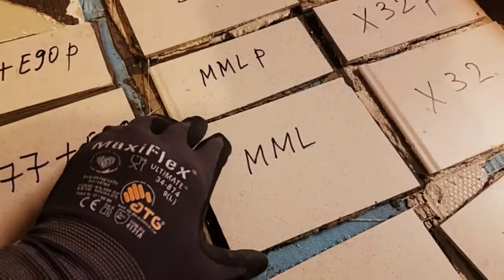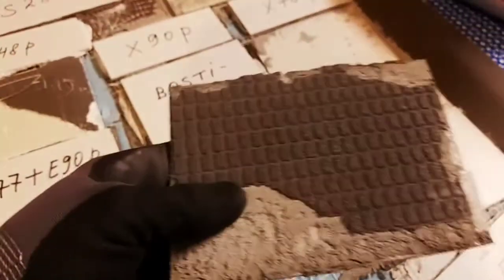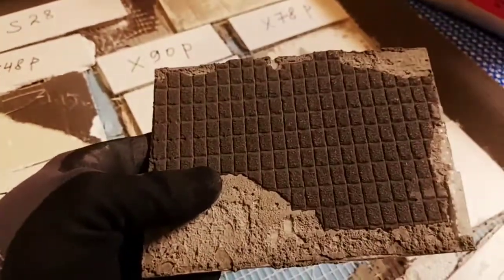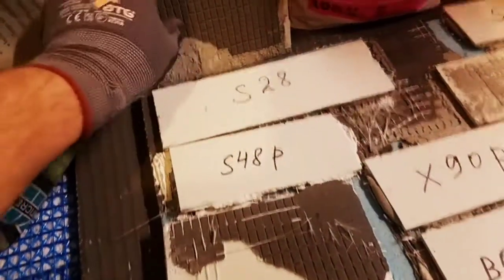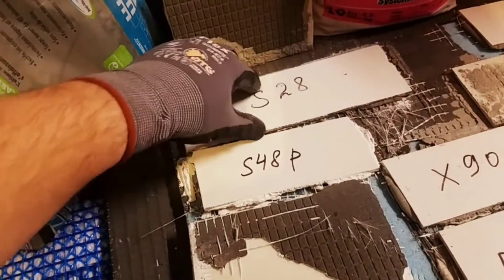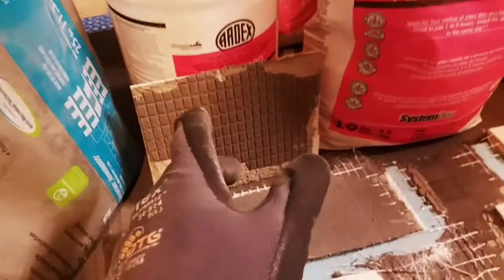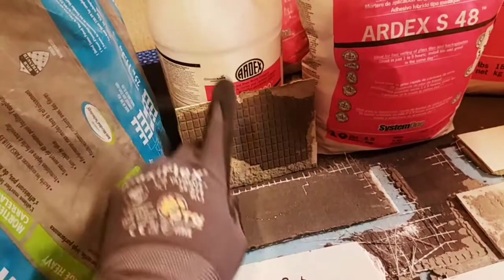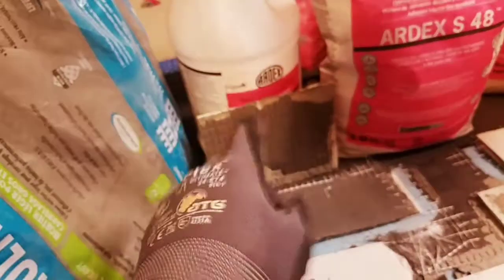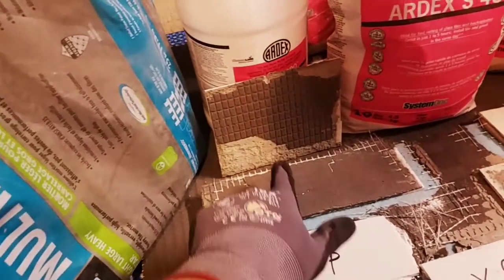and it provides great bond. Now, I was also surprised that Laticrete Multimax Light, applied directly to resin backing, also showed very great adhesion to resin backing. So these two mortars, Ardex S28 and Multimax Light, have something in them that produces very strong adhesion and bond even to resin backing. But at the same time, we have to know that neither Ardex nor Laticrete recommends these two mortars to be applied directly to resin backing. So it is important for us to follow manufacturers' recommendations to stay under their warranty.